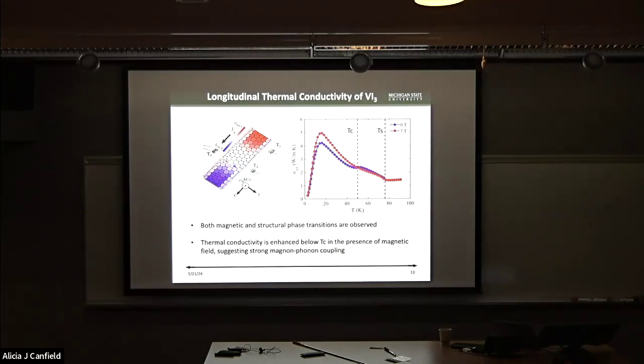Now let's take a look at the longitudinal thermal conductivity first. So this figure shows the longitudinal thermal conductivity, so-called kappa XX, as a function of temperature. We measure at zero field and 7 Tesla. And immediately we can see that the system shows two anomalies. One occurs at the structural phase transition, the other occurs at T_M. This is highly reproducible, as I'm going to show you in one of the next slides.